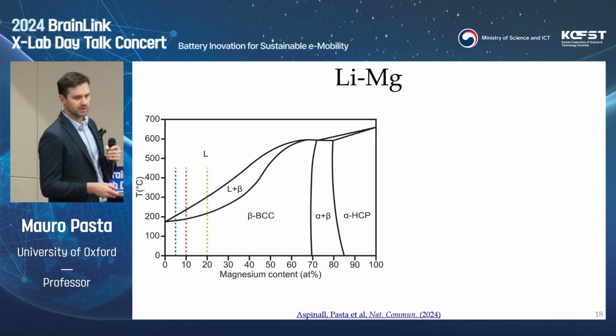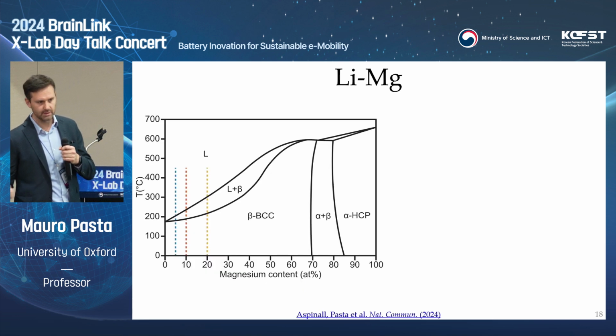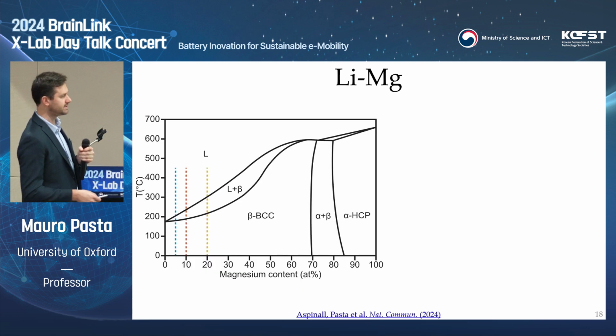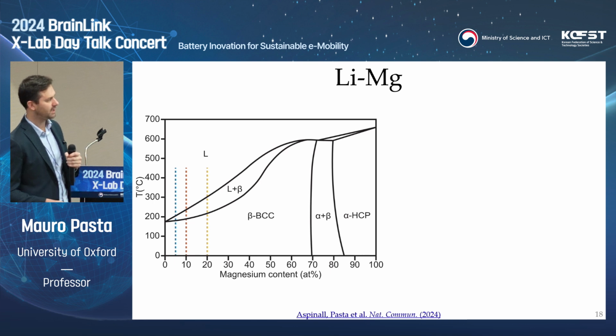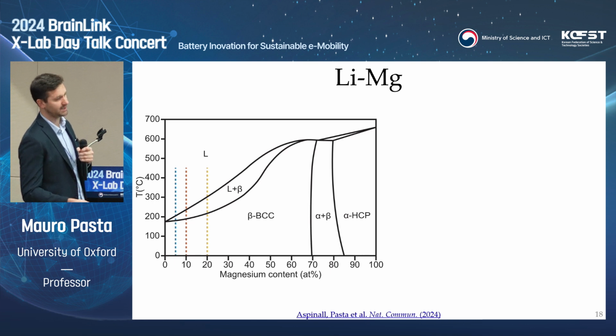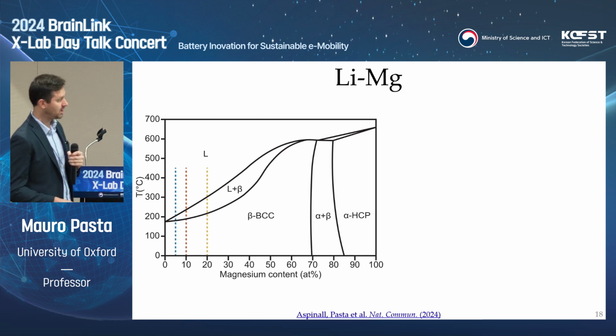I'll give you an example today, which is the lithium-magnesium system that we have looked into in quite a good level of detail for a few years now. I think it's a very good model system and also a very practical system, as I'll show you in a second. What's special about the lithium-magnesium system is the phase diagram. You can see you can dissolve quite a big amount of magnesium in this system until you reach 70% magnesium in lithium, retaining the same BCC structure. So this is effectively a solid solution of magnesium in lithium.